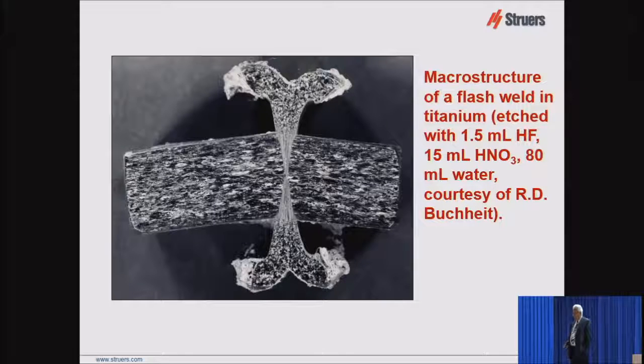This is a flash weld in titanium, and it's nice, when you're doing this kind of stuff, to leave all the burrs and things on there, because when you look at them microstructurally, they add excitement to the image. But of course, in service, you wouldn't want to leave this junk sticking there. You'd grind that off. But this is etched with an aqueous solution with 1.5 milliliters of hydrofluoric acid, 15 nitric, and of course 80 milliliters of water. And it was done by Dick Buchheit also.